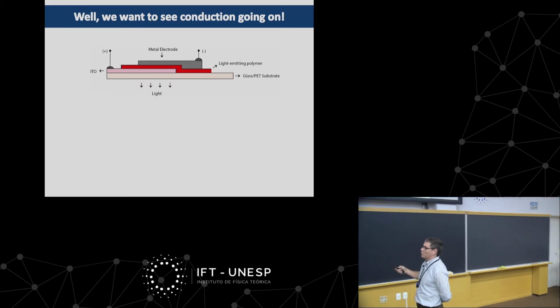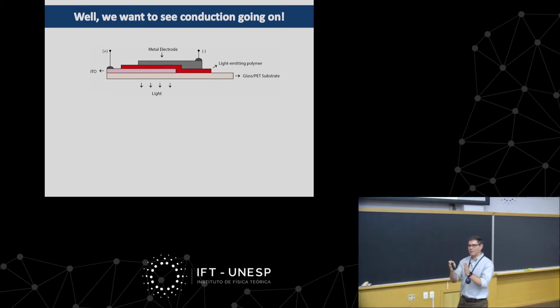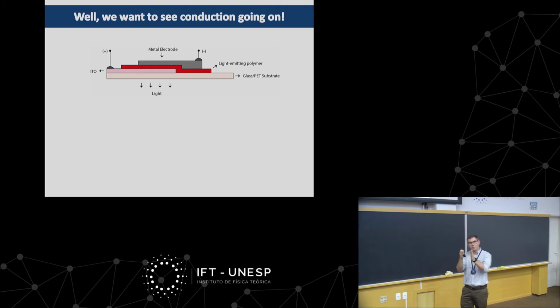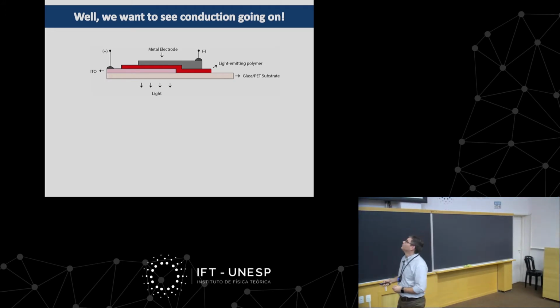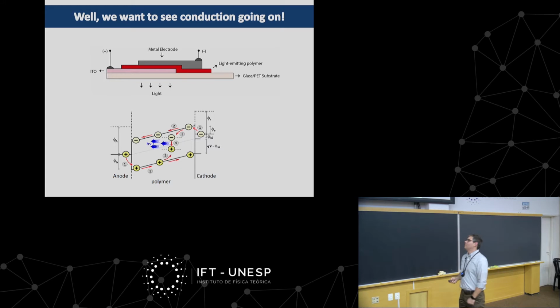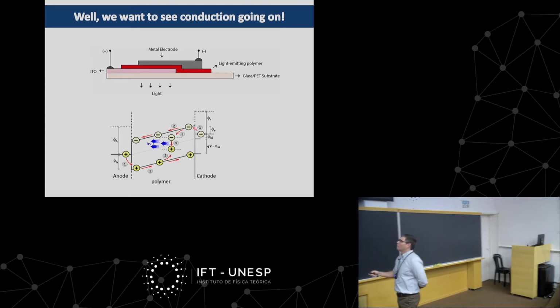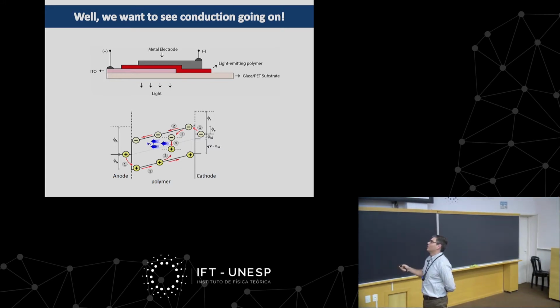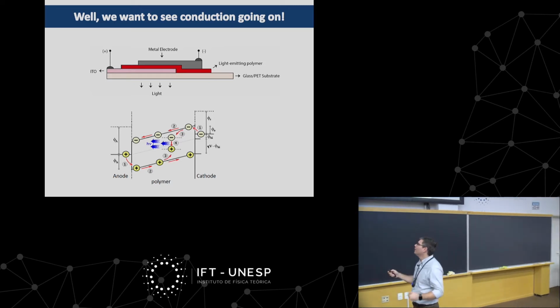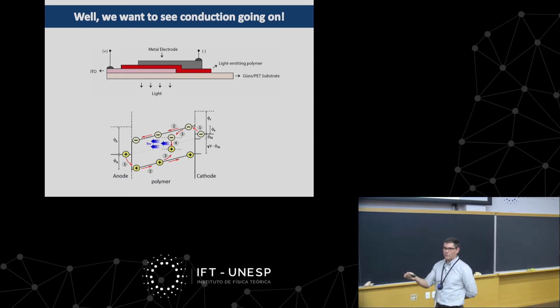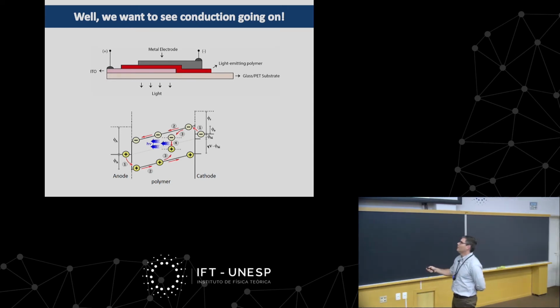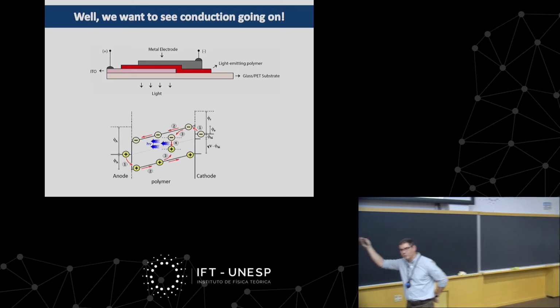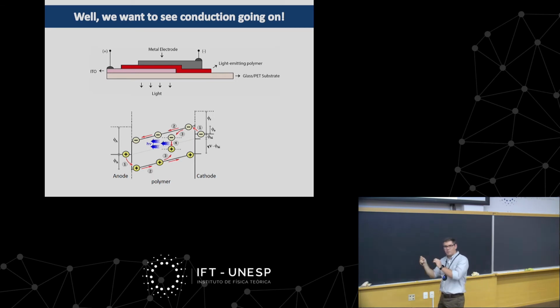So now you have what we call a sandwich type of device, where two electrodes sandwich a polymer layer. And the way this device works is quite simple. Of course, the ITO, the transparent oxide, and the metal electrode, you have to pick properly. You want to pick the work function of these materials, metals or oxide, to match the valence band and the conduction band of your material, because otherwise you're going to have to give energy for charges to be injected into or removed from the material.